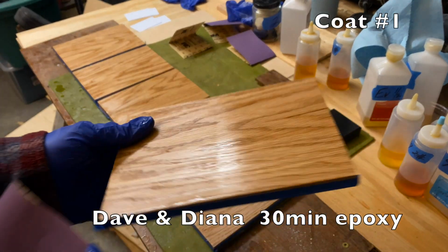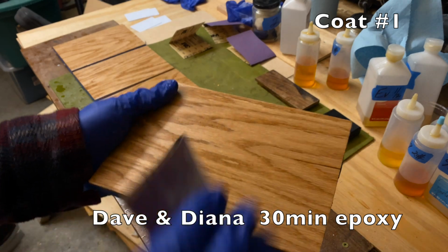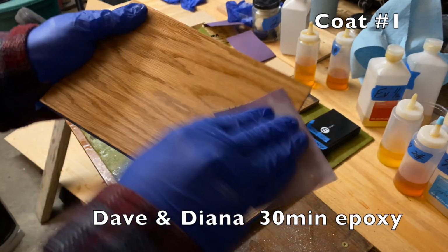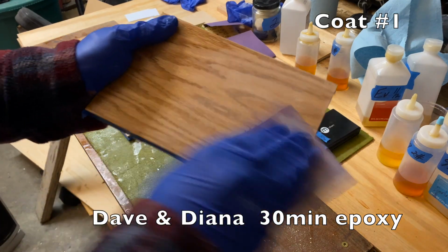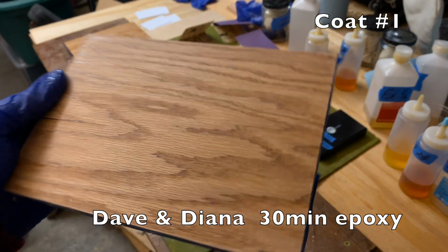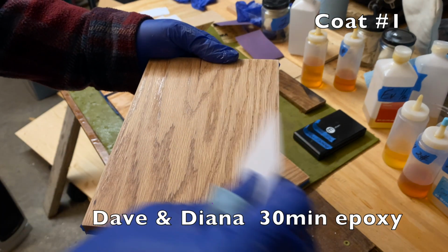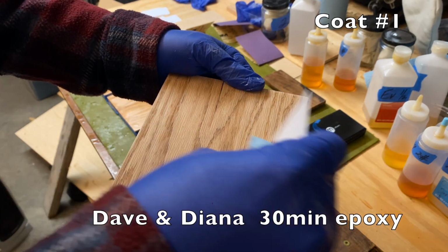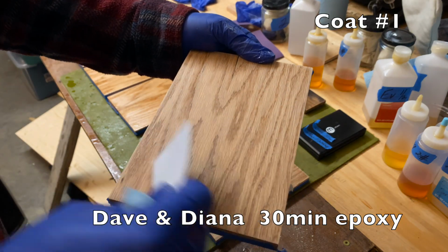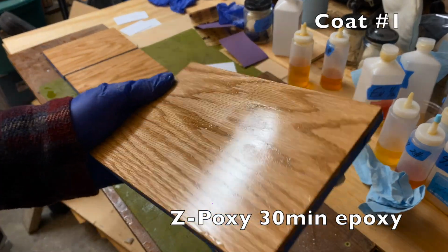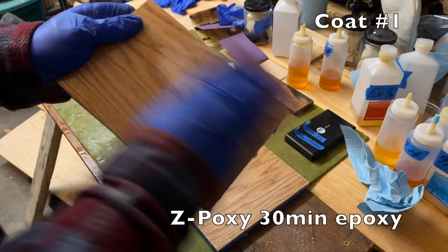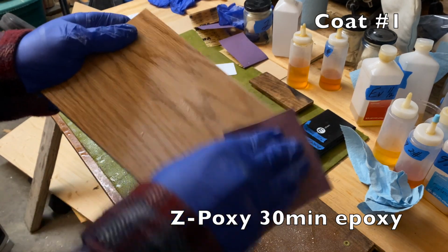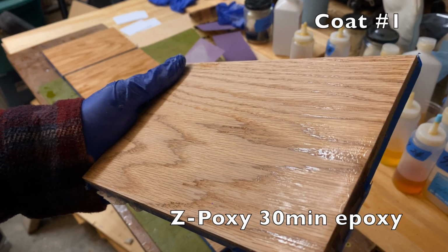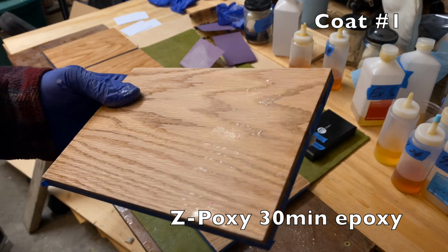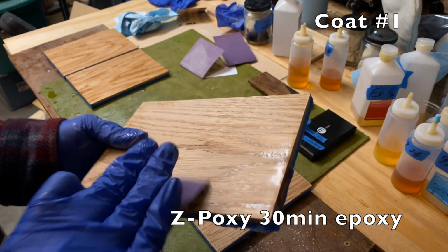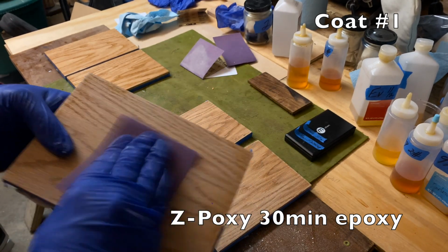Next up is the Dave and Diana Crystal Clear Epoxy Resin, and it also responded quite well to the 320 grit sandpaper. So far, both the Z-poxy finishing resin and this one have responded more like a finishing material than a glue, in my opinion. The Z-poxy 30-minute epoxy, on the other hand, took a bit more muscle and effort to sand with the 320 grit. And you can see here that there are numerous shiny areas and missed spots after spending a good amount of time with the 320. So I eventually dropped down to a 220 grit paper to finish the job.